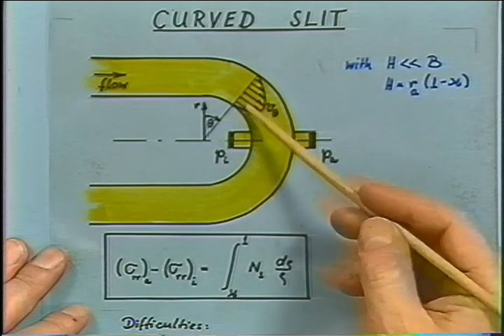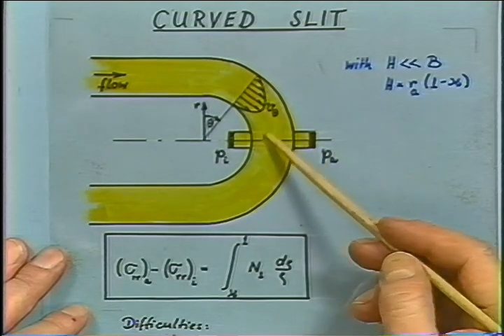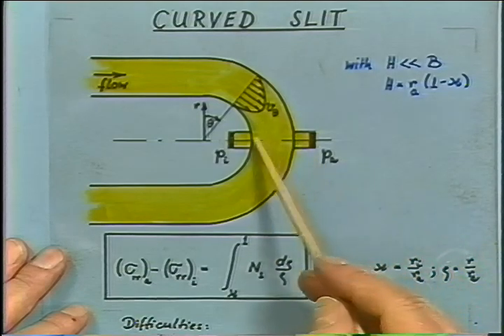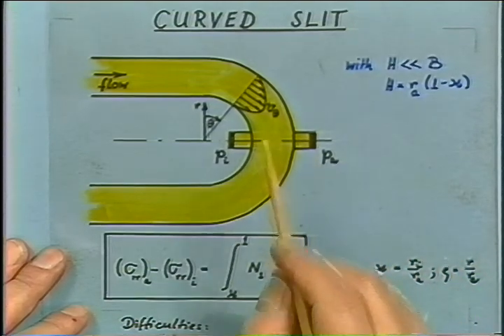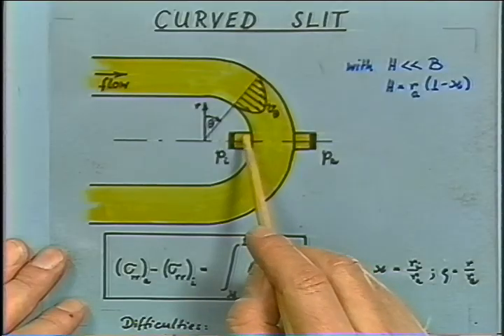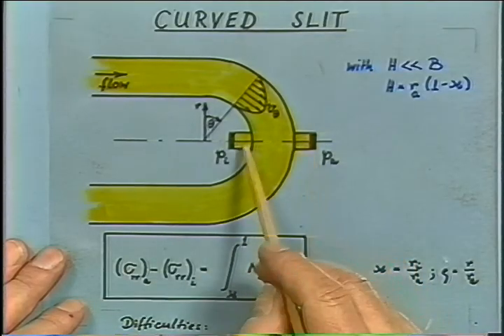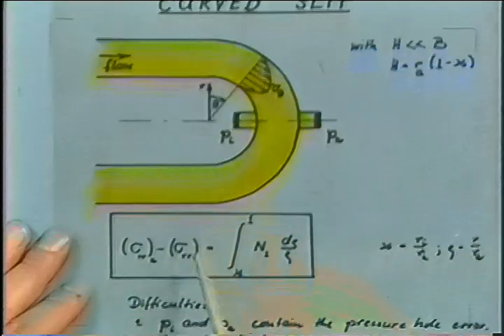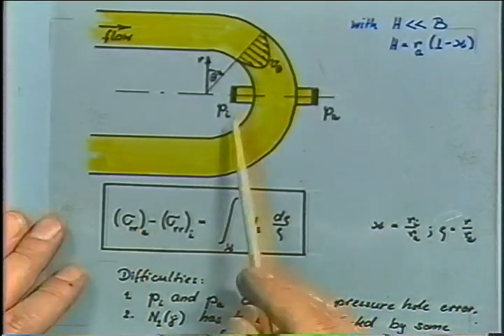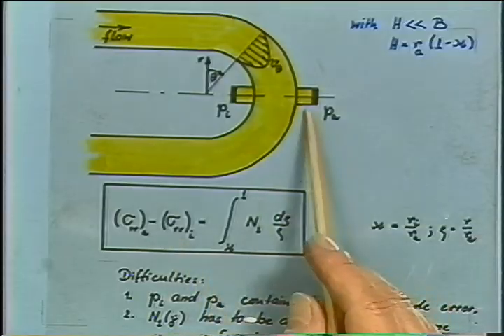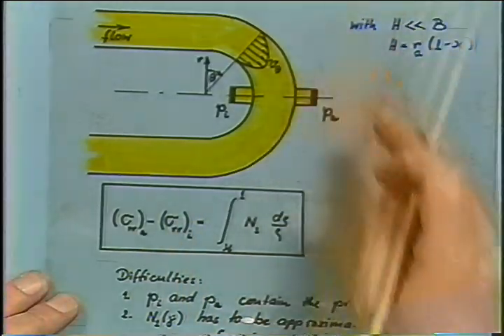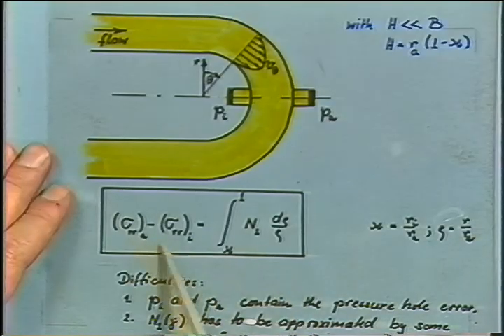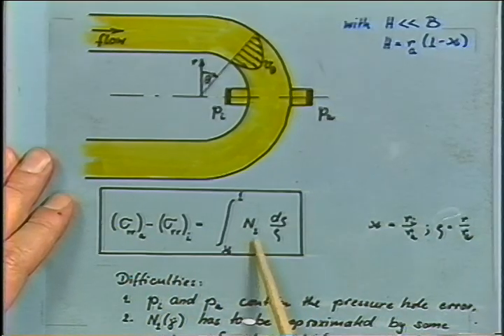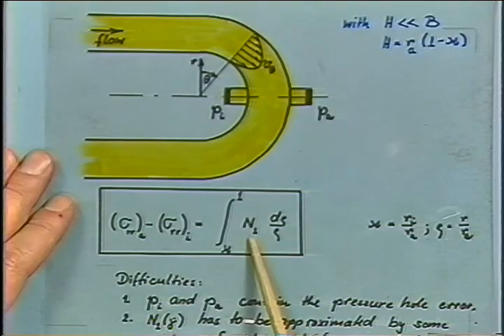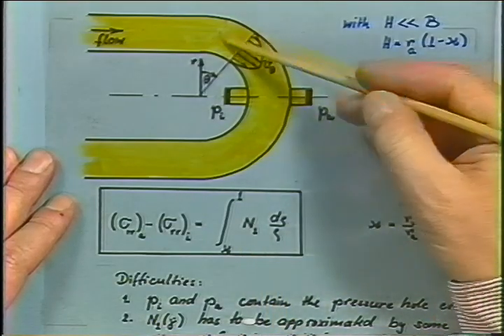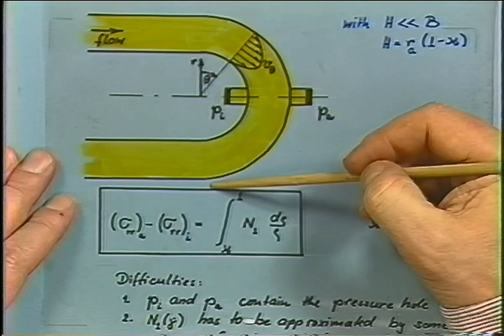And due to that tension, the streamlines would try to shorten it, and will try to pile up on the inner cylinder. So there will be a higher pressure at the inner wall than at the outer wall, or the radial normal stress, sigma RR, at the inner wall is higher than the radial normal stress on the outer wall. And the difference, again, is given with the normal stress function. In this case, it's the first normal stress function because it's dominated by the tension in streamline direction.